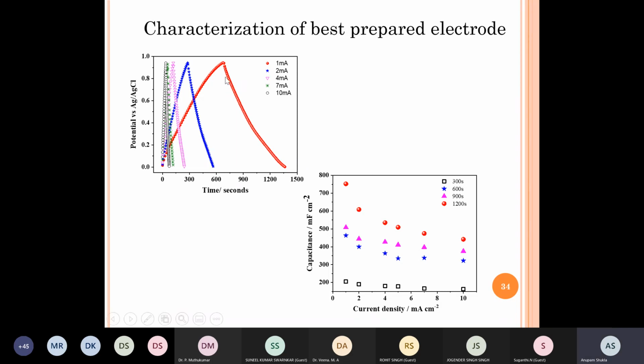So here is a galvanostatic charge discharge curve that we showed earlier. In an ideal capacitor, which is never found, you will have a triangle, a straight line going up and a straight line going down. In a real device, you will have a slightly curved, but still more or less linear line. So here is the performance. These are at different current densities, 1 milliampere per centimeter square to 10 milliampere per centimeter square, and what kind of charge discharge curve it gives. Based on this charge discharge curve, one can calculate the areal capacitance, that is capacitance per unit geometric area, and at 1200 seconds, it gave very good results of about 750 millifarads per centimeter square.